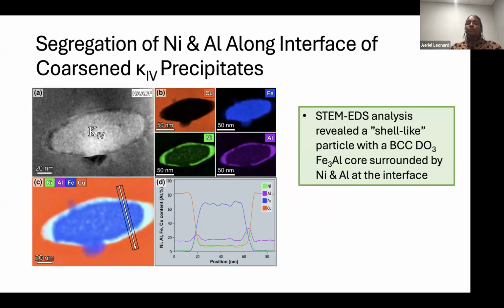And really, what we learned through looking through the literature is this actually was a heat treat phase that could happen at 350 degrees Celsius. And it was very interesting because in the wire arc additive manufacturing process, the chamber itself is kept at 350 degrees Celsius. We didn't plan that. It was right on with what older literature had seen. So we knew that this was a heat treat phase that was actually happening during the processing.